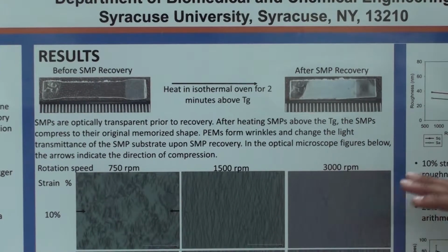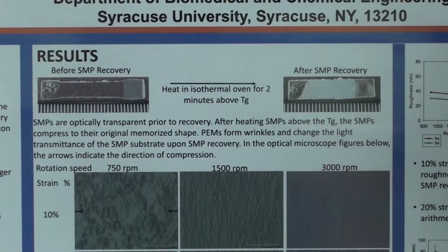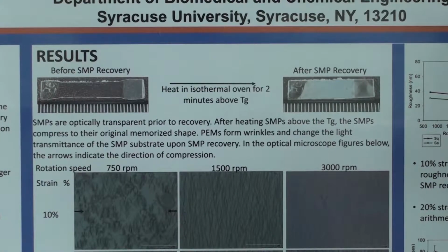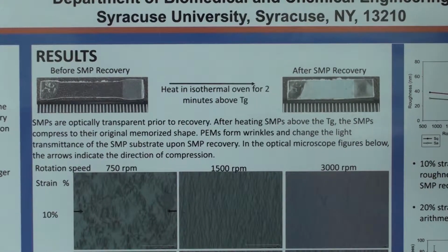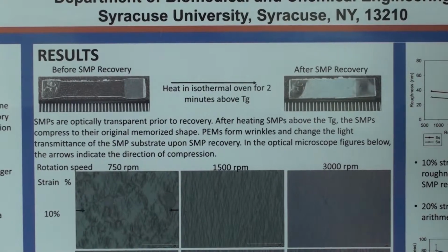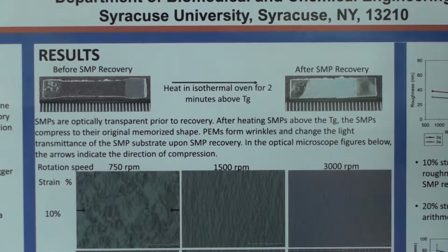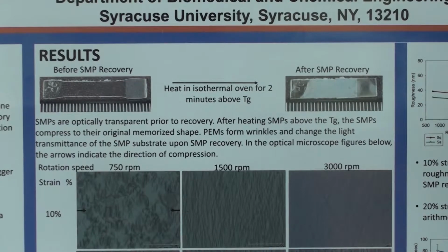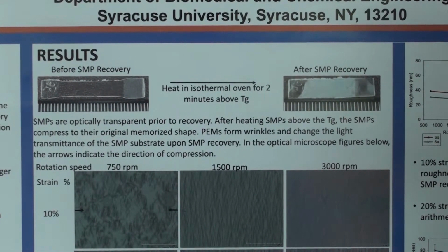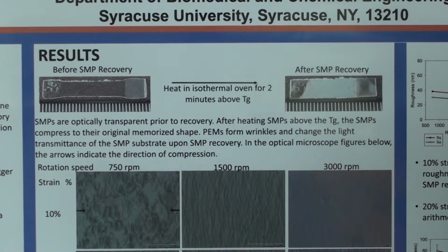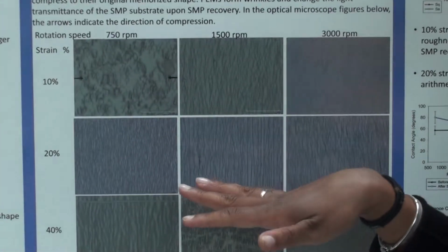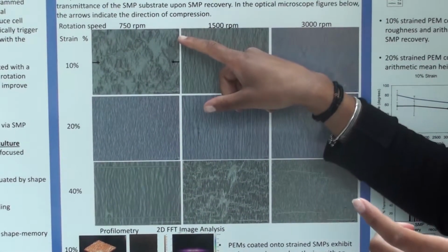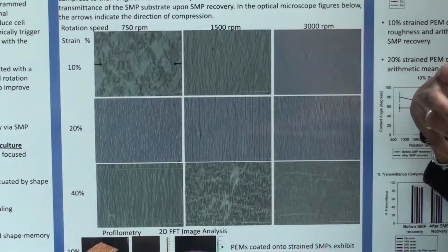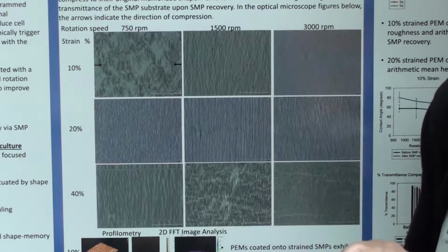So from that we can do optical microscopy, AFM, and profilometry, and really try to characterize the amplitude, or how high the wrinkles are, and the wavelength, or how spread apart the wrinkles are. And this will all dictate how well cells can align on our substrate, which can mimic some cellular environments, like in your arteries. And so what I did is I strained the shape memory polymer to 3 different strain percents, and I varied the rotation speed to create different thicknesses of the polyelectrolyte multilayers, and also a different stiffness of the polyelectrolyte multilayers.